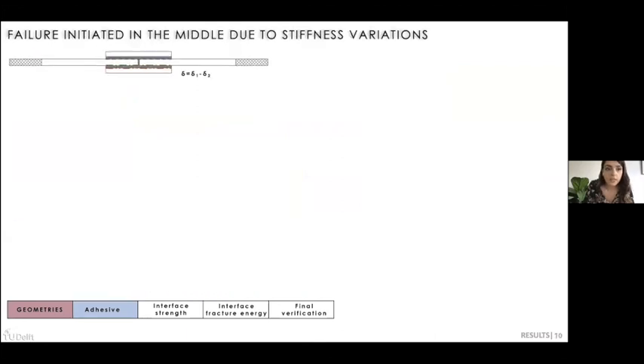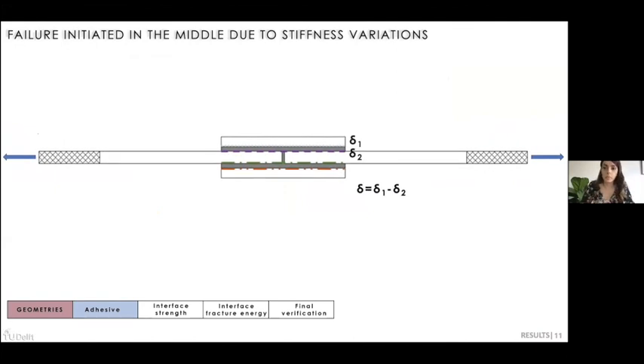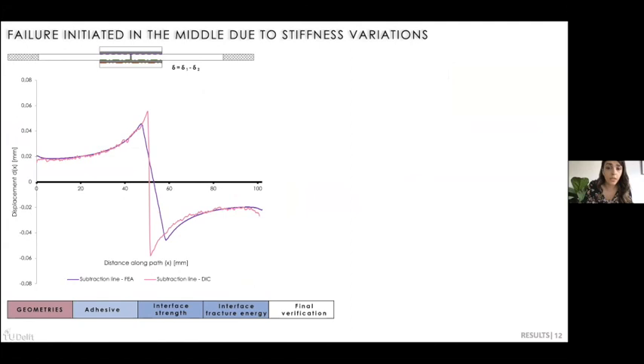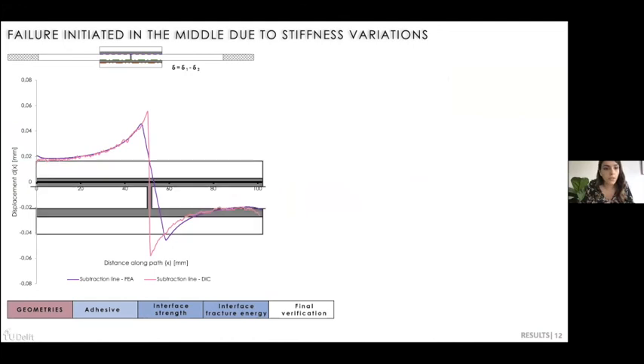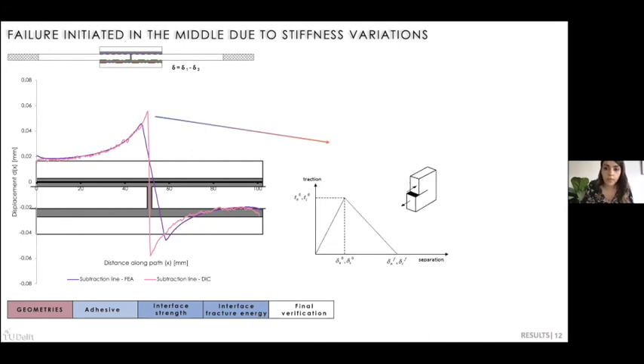So what I did, you can see here, is that I went back to my experimental results from the DIC. I drew 4 lines in the 4 interfaces, and I asked for the longitudinal displacements, meaning the ones in direction of loading. I did the same thing on my finite element analysis. I subtracted those 2, and you can see at the top adhesive layer, I'm going to also point here the double lap joint, yes. You can see that at the top adhesive layer, the concentration of shear differential displacements is higher in the middle of the connection due to stiffness variation. And matching these lines from the DIC with finite element analysis gave me an insight on the interface properties.